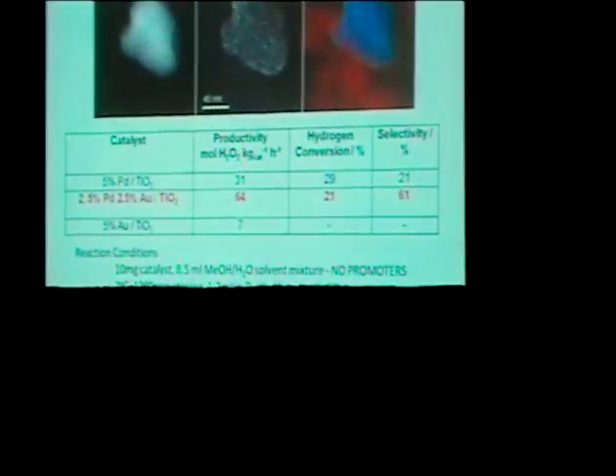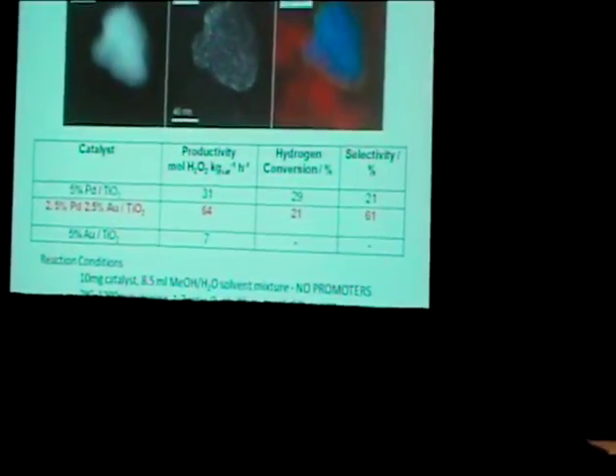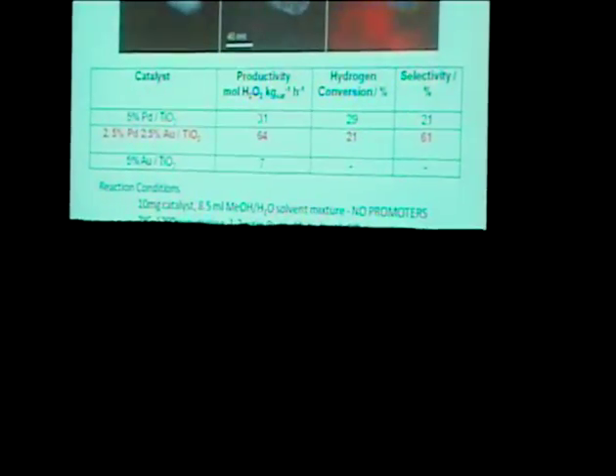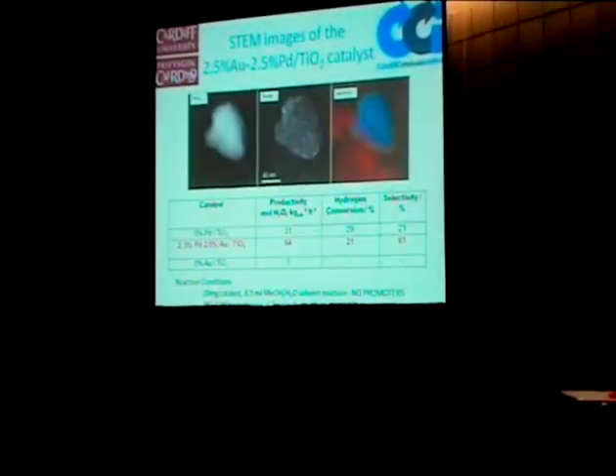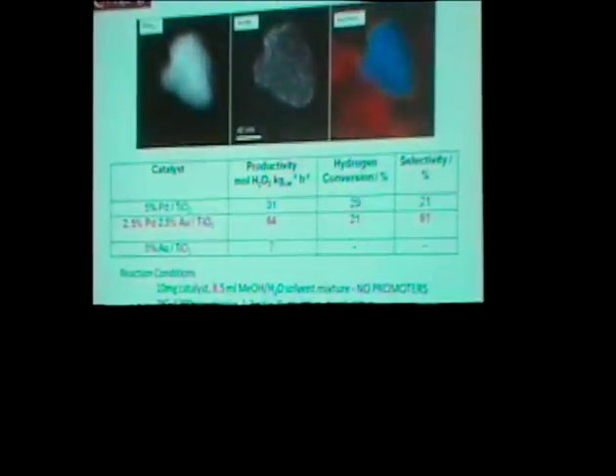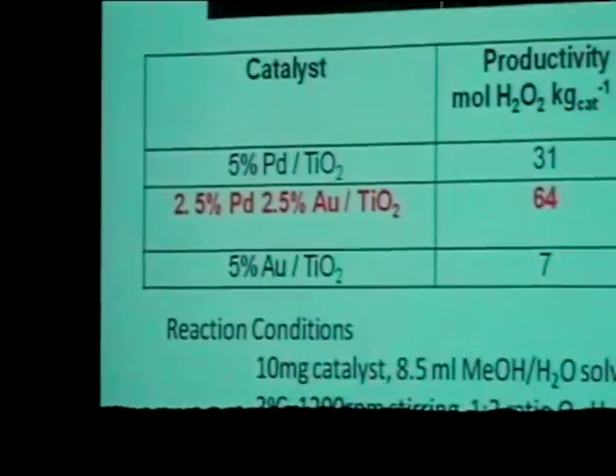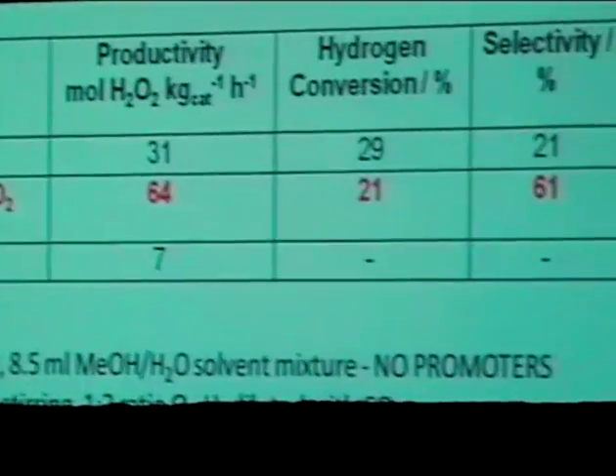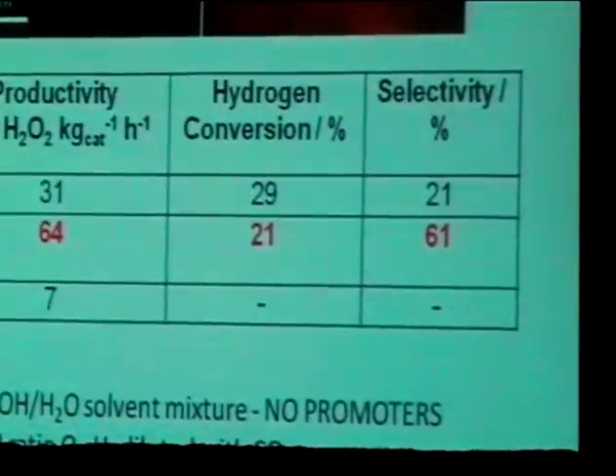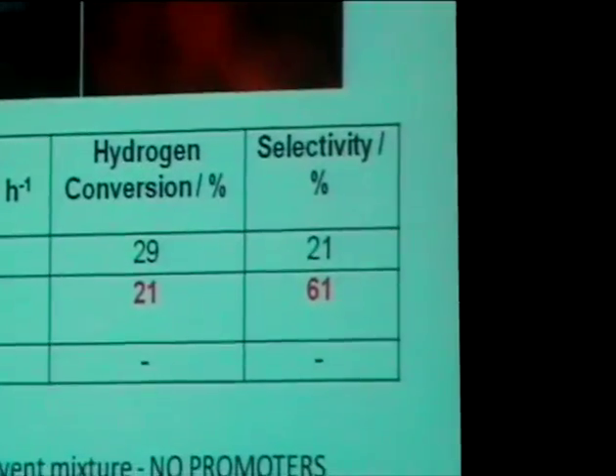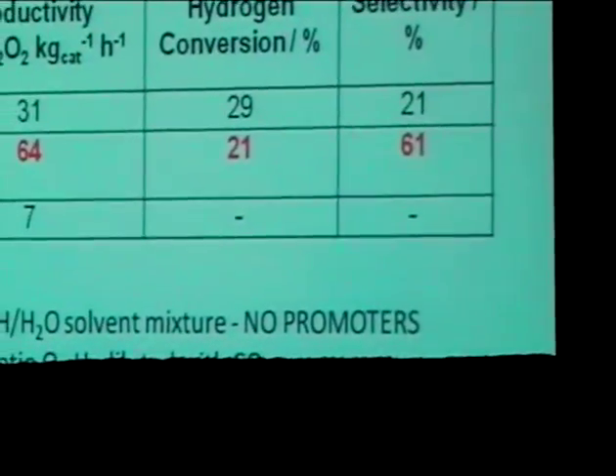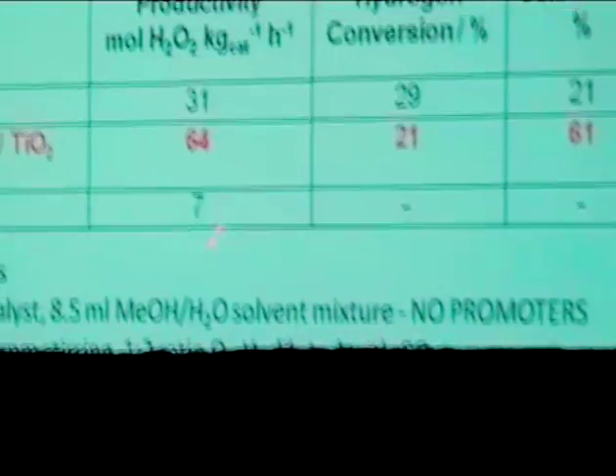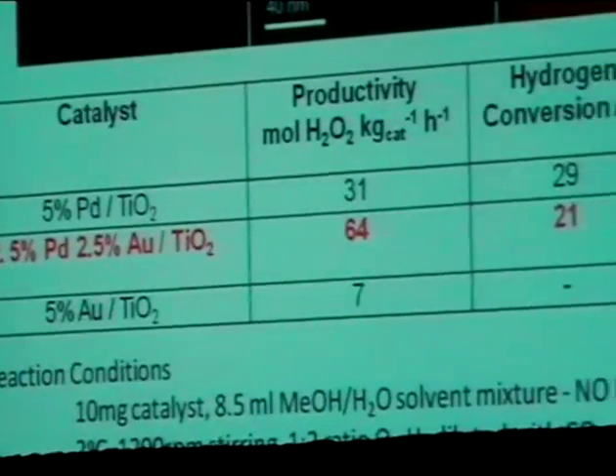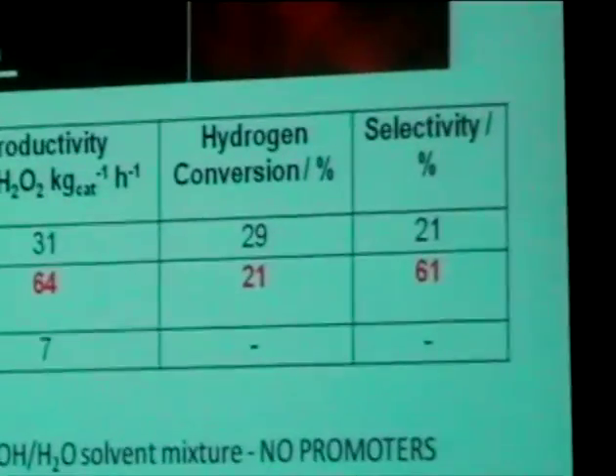We carry out our reactions in the presence of no promoters, and we observe that the addition of gold into these palladium catalysts significantly boosted the activity towards hydrogen peroxide synthesis. This was done mainly by an increase in the selectivity towards hydrogen peroxide. So we see a small decrease in the amount of hydrogen conversion. Gold on its own produces a very small amount of hydrogen peroxide. So this is a true synergistic effect between gold and palladium in these catalysts.